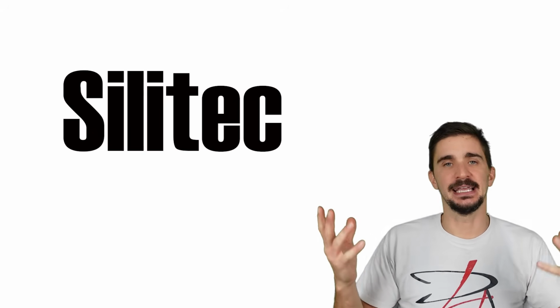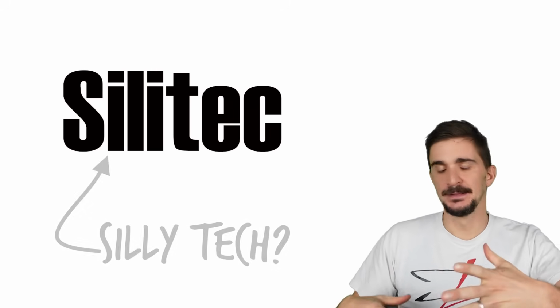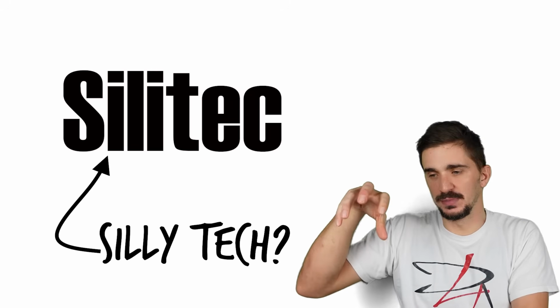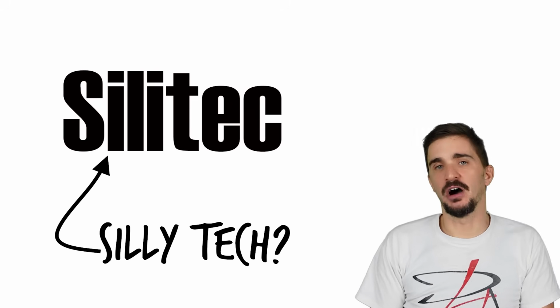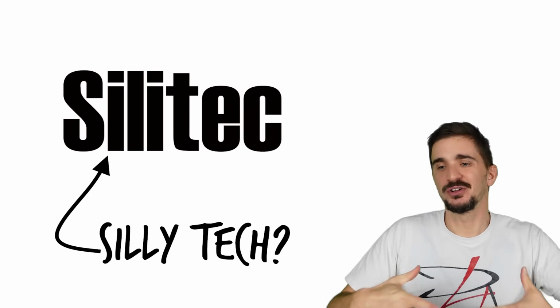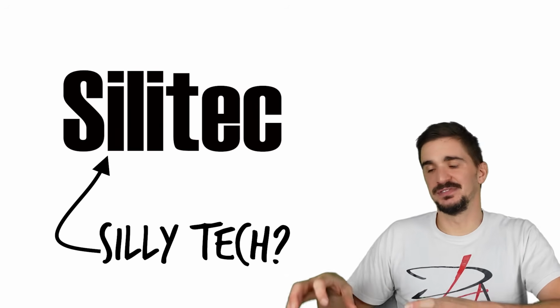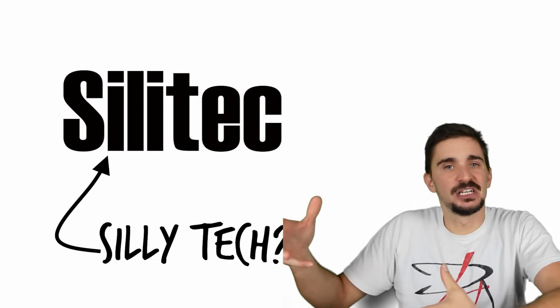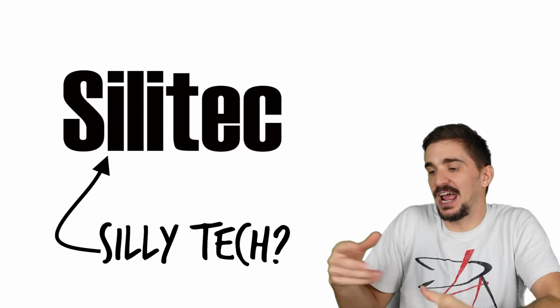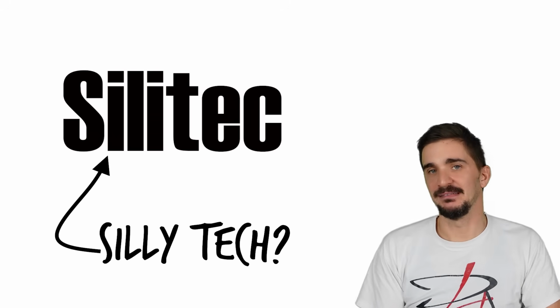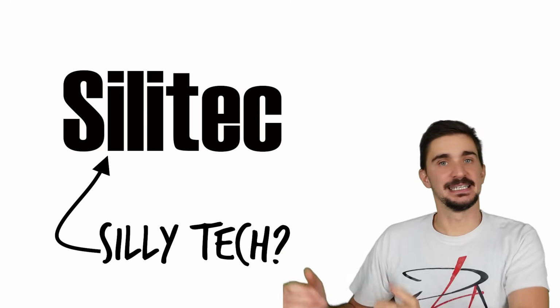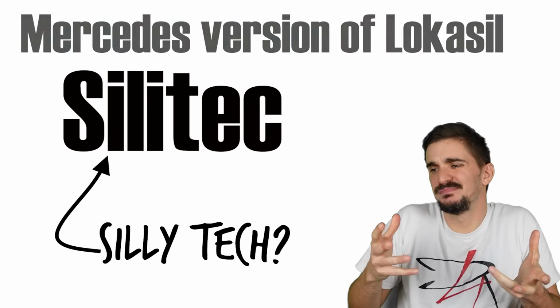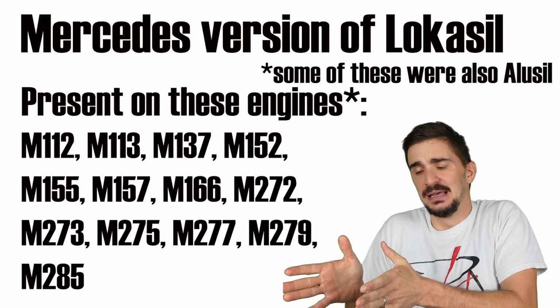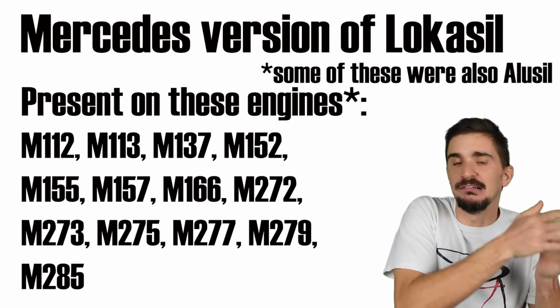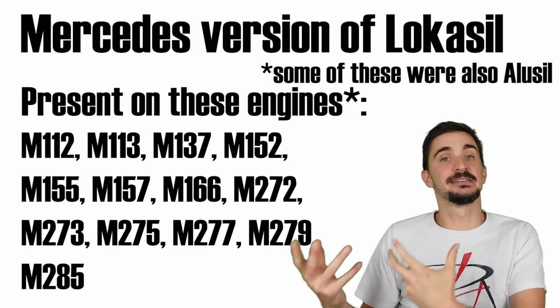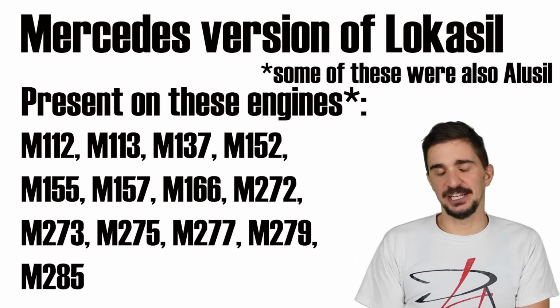Now, Silitec is very similar to Lokasil because you also have a pre-formed liner and then you cast the block around that liner, but apparently it's legally different enough. The liner is of a different composition, and maybe the manufacturing is slightly different, so you don't have to pay license fees. In fact, Mercedes doesn't have to pay license fees because you can sort of think of Silitec as Mercedes' version of Lokasil, because Silitec is almost exclusively used on Mercedes engines.